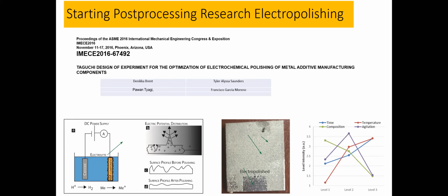In order to optimize, what set of variables are important for us? We have started playing with time, composition of the bath, temperature, and agitation. We played with a number of levels for each to come up with the optimum combination. We generally use a design of experiments approach. This work is shown in a paper on Taguchi Design of Experiment for optimization of electrochemical polishing. So this has been published.